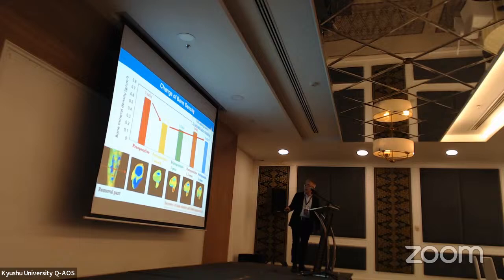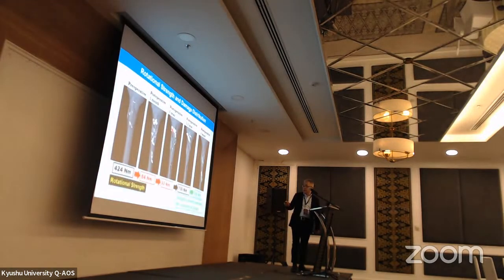So then we measure this strength, rotational strength. Under this pre-operative condition, the strength is 424. But after 1 month, under the post-operative condition, the reduction of strength is very large. Then after that, at 1 year, 1.5 years, and 2 years, strength is slowly recovering. Now, 2 years later, the strength is about 40%. Okay, so that's why this patient must still be very careful when she applies load to her tibia by rotational movement.